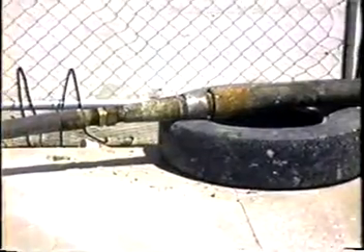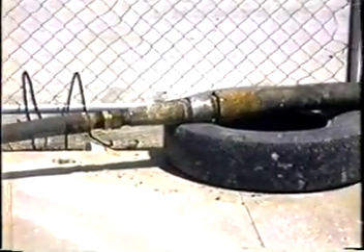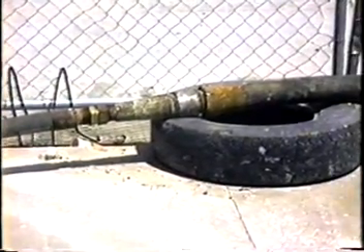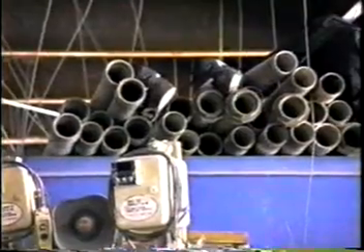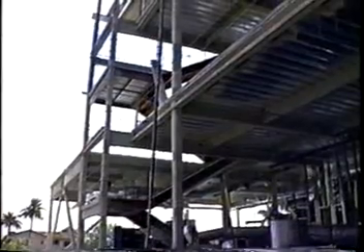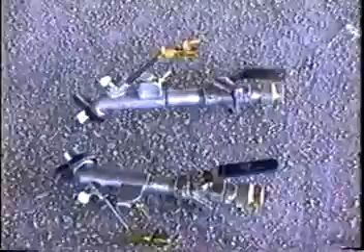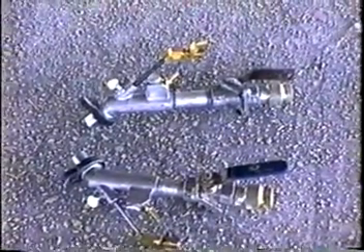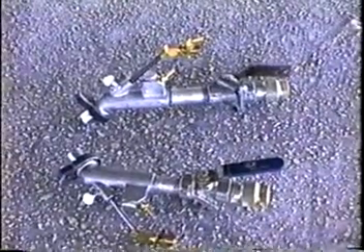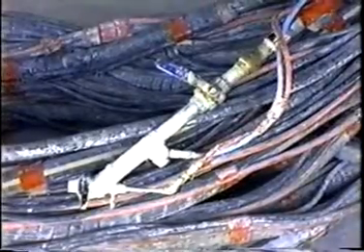Maximum hose lengths for different diameter hoses should be in accordance with those listed in the application manual. Tapered reducers must be used when a reduction in hose diameter is necessary. Metal standpipe 2.5 inch to 3 inches in diameter must be used when pumping height exceeds 3 stories or 36 feet, or when required hose length exceeds 335 feet. The spray nozzle assembly should consist of a minimum 1 inch inside diameter aluminum pole with blow-off type nozzle cap, nozzle orifice, and material and air control valves.